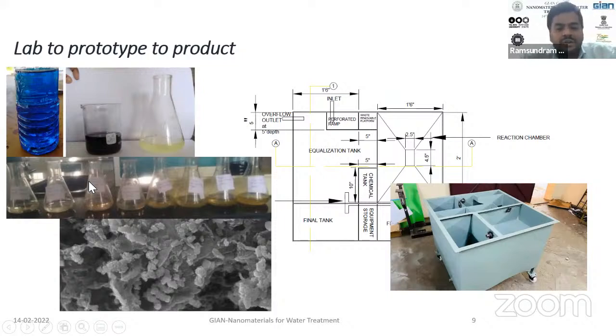Whether you say iron oxide is working well or graphene is working well, it is all dependent on the temperature and the pH you are operating on. So it's a customized size of reactor which we developed, and this balances the pH first, then it equalizes the temperature. What is the temperature equalization here? We maintained about 26 degrees Celsius, but it is very difficult to work on. But we found a range of 26 to 32 degrees Celsius where the performance is almost okay.